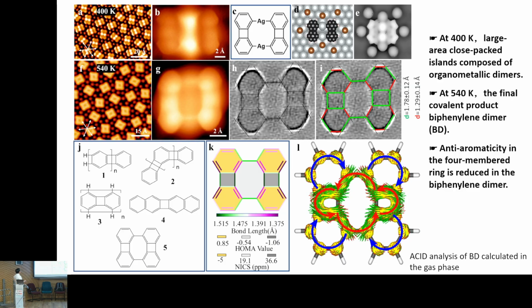If you further increase the temperature above 400 Kelvin, now you form this thing here, and this STM, in Laplace-filtered images, tells that you can see this formed four-membered, six-membered, and eight-membered rings here.